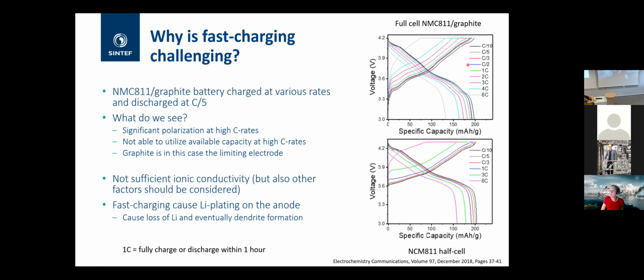What we see here in the top figure is that when you increase the charge rate, you have great polarization, and you see a drastic decrease in the capacity. So the overpotential is just growing. That means that you're not able to utilize all the available capacity when you increase the C rate.